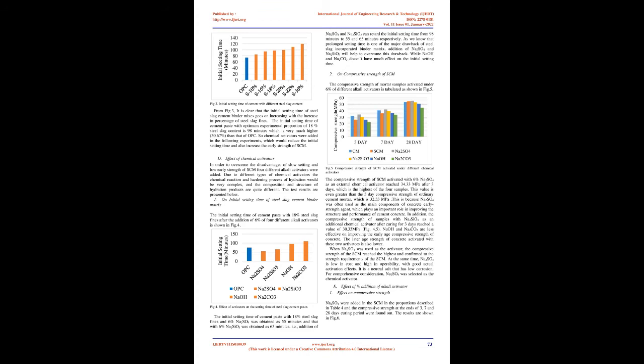With the progress of time, hydration products became matured and their filling effect was also increased, resulting in a more compact structure. In order to get a more accurate optimum, SCM specimens were prepared with 16%, 18%, and 22% steel slag content and the corresponding compressive strength were shown in Fig. 2. Fig 2. Compressive strength of SCM with different steel slag cement ratios.